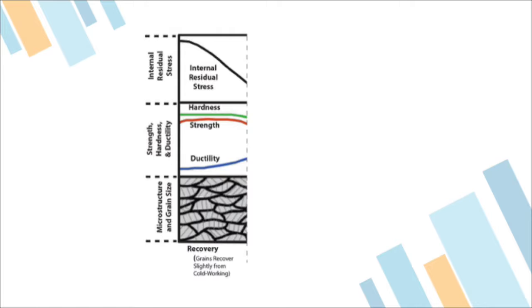The first step is recovery. This usually occurs at low temperatures and involves the motion and annihilation of point defects, as well as the annihilation and rearrangement of dislocations, resulting in the formation of subgrains and subgrain boundaries. A distinctive feature of this recovery process is that it does not involve any change in the grain structure of the cold-worked metal. The only changes taking place are the dislocation arrangements within the existing grains.